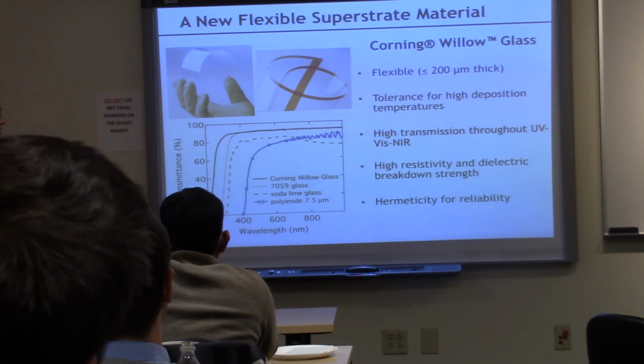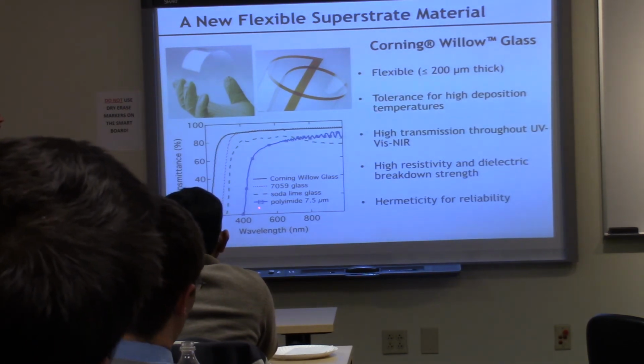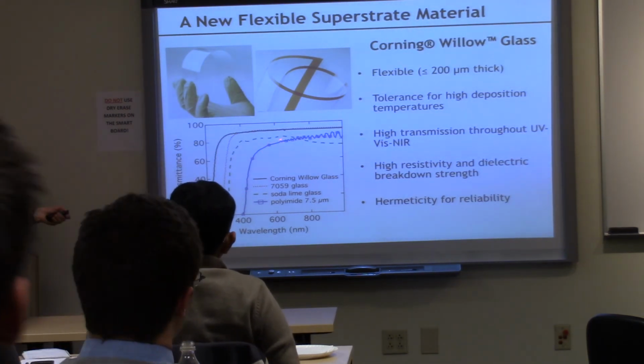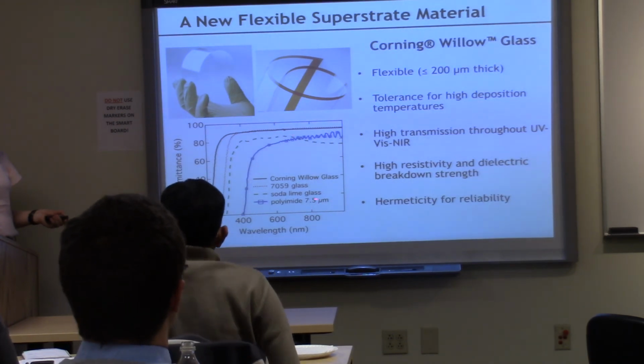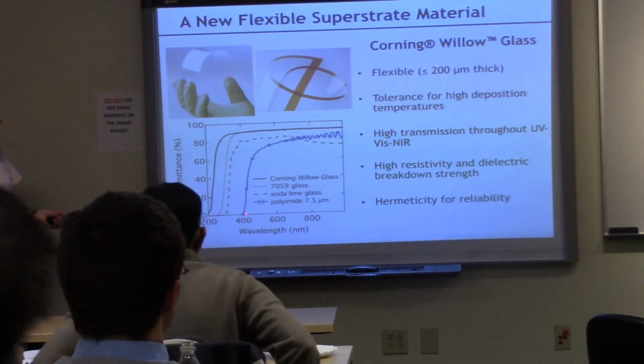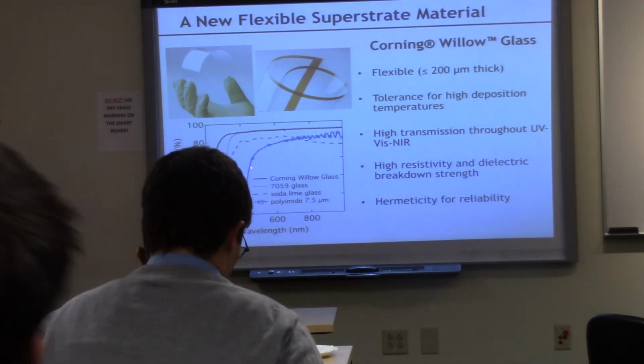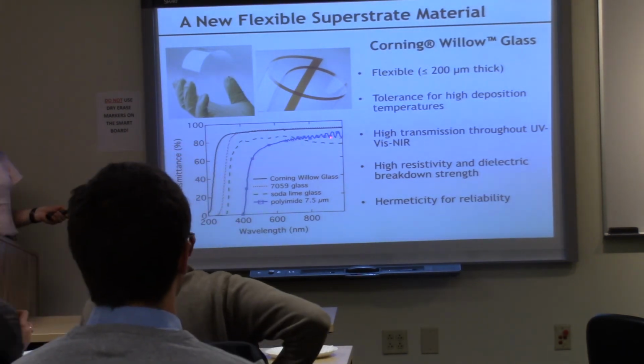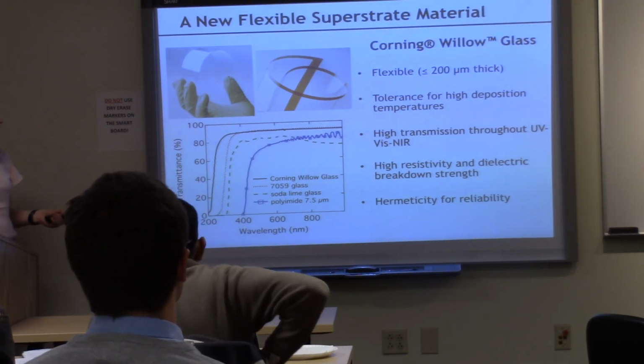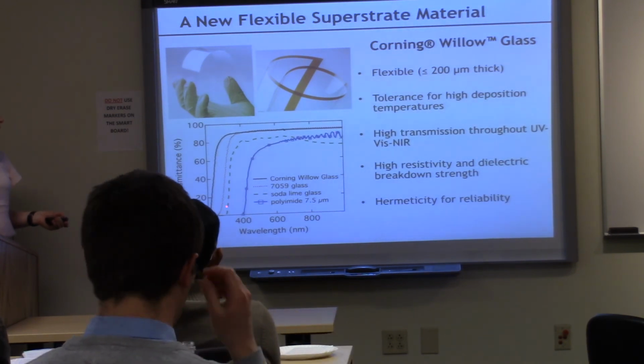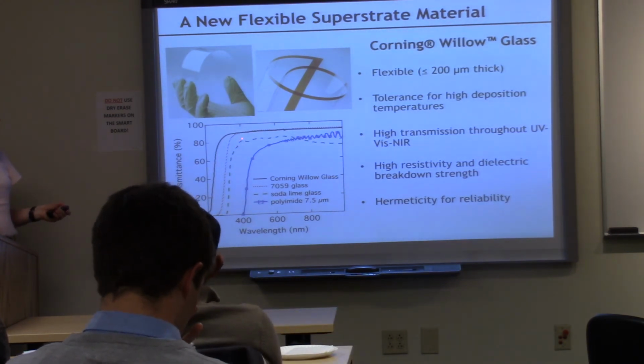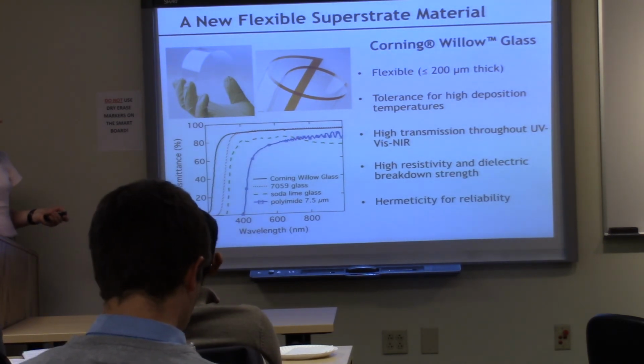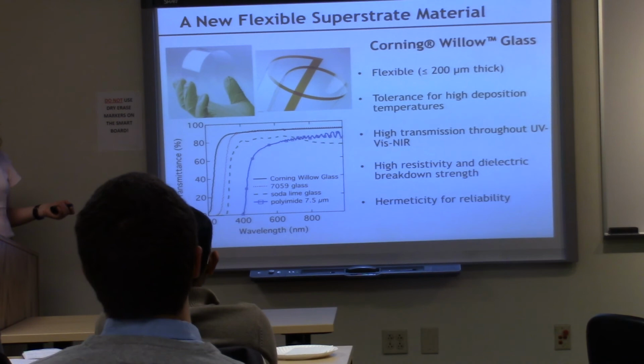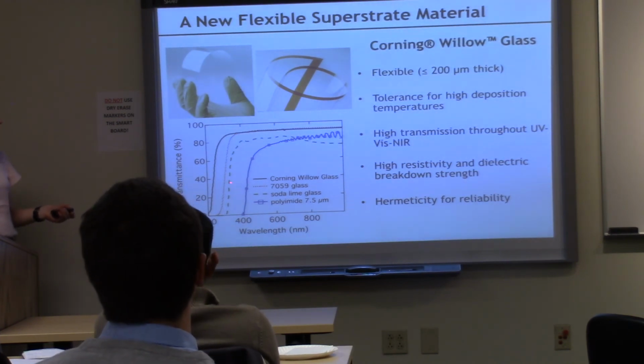Here I'm showing the transmittance of a couple different kinds of glass and the standard polyimide. This is the high transparency, really thin polyimide that people use. You can see it has an absorption edge cutoff at about 400 nanometers and a lot of features going out towards the red. If we look at soda lime glass, this is iron-containing soda lime glass, so it's still got quite a lot of optical absorption. This is not accounting for reflection, assuming reflection for many of these would be similar. Here's our old standard technical glass.